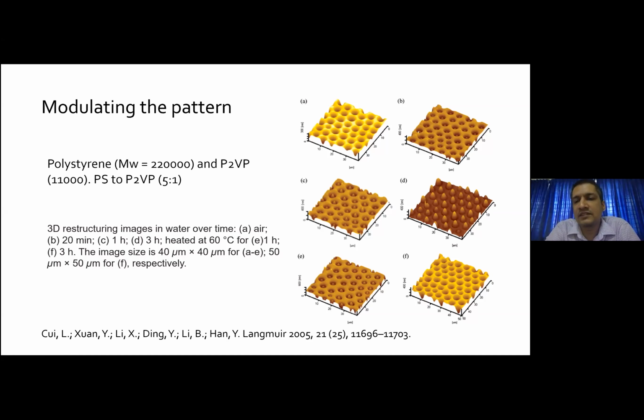And the swelling results in the evolution of pillars. As you can see, if you increase the exposure time of the ethyl alcohol on the already prepared breath figure, you get these kinds of protrusions coming out of the places where there were initially wells. And these are all due to the swelling of poly(2-vinylpyridine). So once you get this swelling done, can you make it go back? Yes, you remove it by heating at around 60 degrees for 1 hour, 3 hours and so on. So you get back the same pattern that was there earlier.